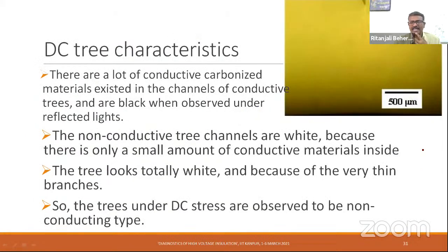DC tree characteristics. How can we characterize the DC tree? In the AC tree, it was mostly carbonized, partially carbonized or conducting, partly conducting, partly non-conducting. But if we leave it over time, mostly it becomes a conducting channel. It becomes completely dark in the photographs. However, it is observed in the case of DC, these channels, till they reach the ground electrode, are very thin. In fact, it is light in color from the reflected light, which shows that they are very, very thin in dimension. There are a lot of conductive carbonized materials in the channels of conductive trees and they are black. The non-conductive tree channels are white because there is only a small amount of conducting material inside.